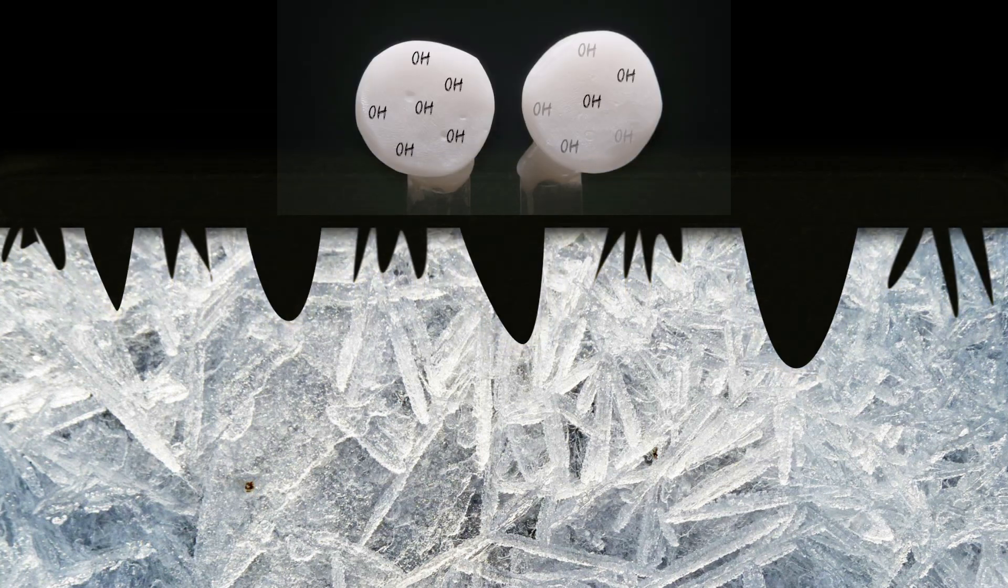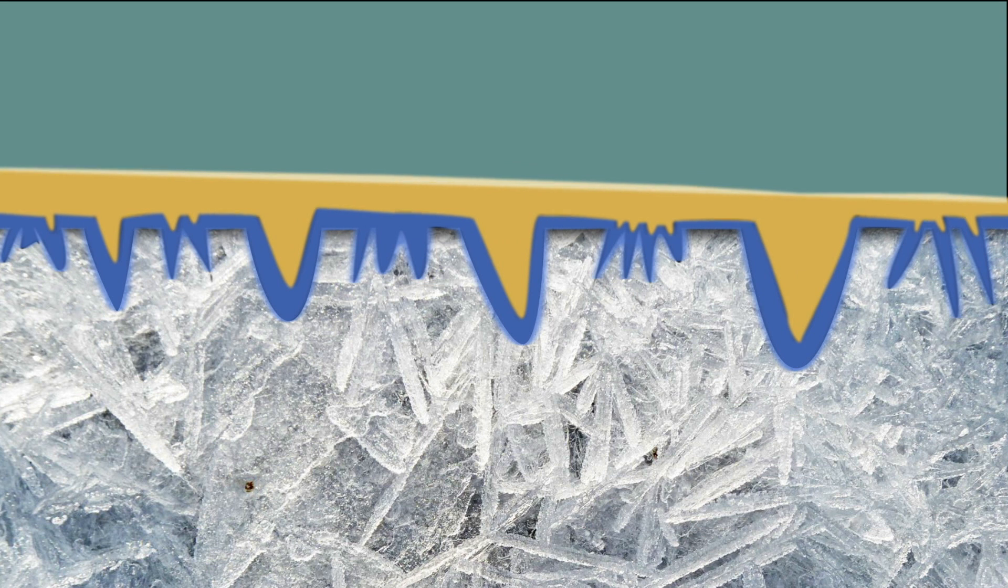Less glass phase, less etching time. Etching of the glass leads to the formation of pores, roughness and the formation of hydroxyl groups which are necessary for silanization. Due to the appearance of roughness, the area and wettability of the surface increase, which is closely related to the value of the contact angle. As a result, it promotes a deeper penetration of the adhesive systems and, accordingly, an increase of the adhesion strength.